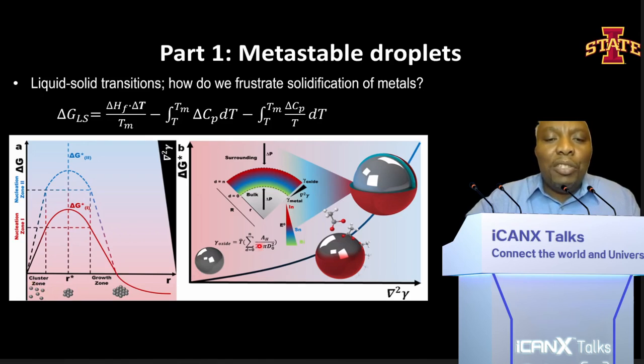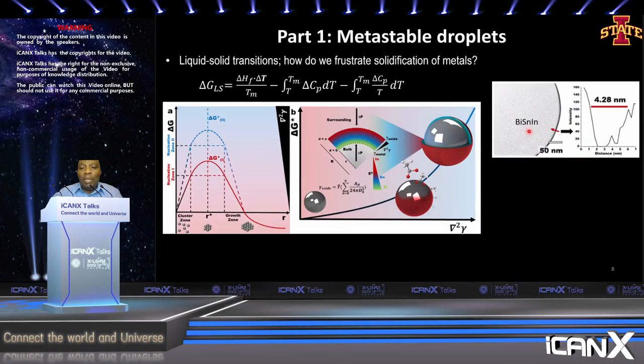And our approach, as I mentioned, is to engineer this surface oxide here and make sure that this provides a tensor component, a stress of some sort that will raise the free energy barrier such that these nuclei don't grow, and they require a lot more energy to actually grow to a point where they can cause nucleation. And so the first metal alloy we looked at was bismuth indium tin, a 3-component alloy, and we found that the oxide layer here, even after growing it for weeks, was less than 5 nanometers.